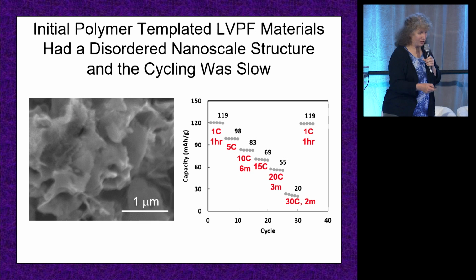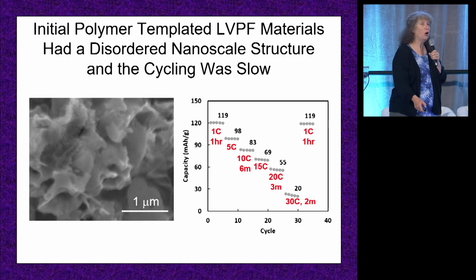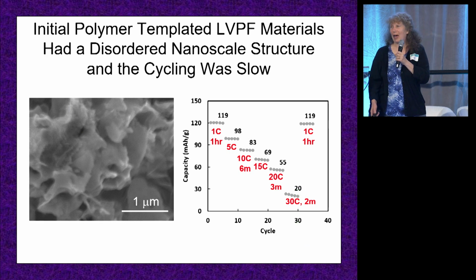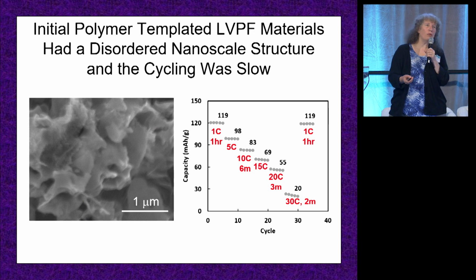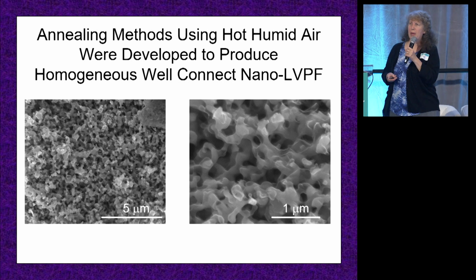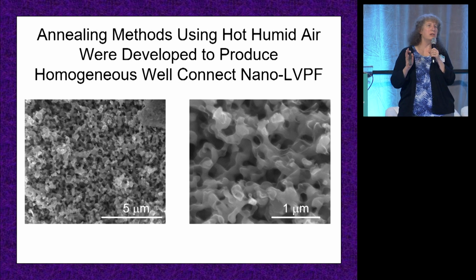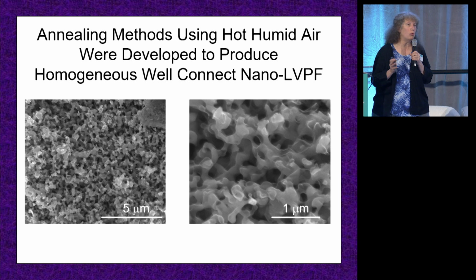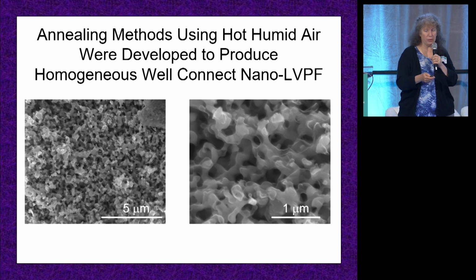So our initial materials had no nice nanoscale structure, and when we went from a 1-hour charge to a 2-minute charge, we lost all of our capacity. So we said, okay, how do we optimize this? And so over the course of this program, the folks who have been involved here have done a huge amount of work developing conditions where they could make really homogeneous nanoscale materials through low-cost methods. In particular, they developed a basically hot water vapor annealing method that could produce homogeneous nanoporous materials.